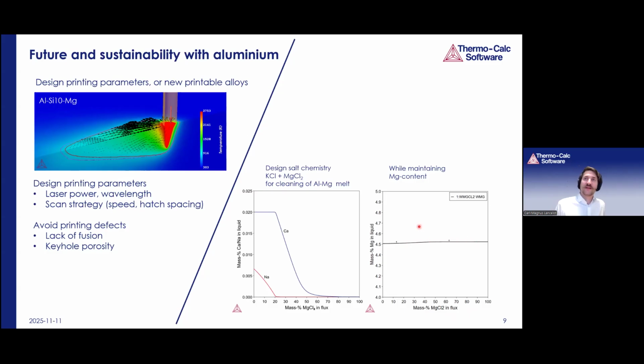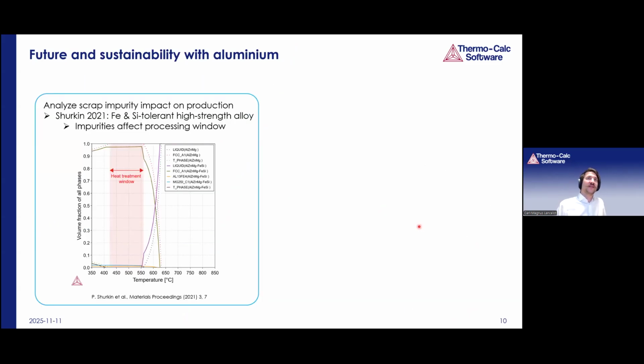So we can see that while increasing the magnesium chloride in the flux, we don't add very much magnesium to the aluminum melt. And then looking forwards into the future of scrap-tolerant aluminum alloys, there are several publications out in literature where Thermo-Calc is used to design new types of scrap-tolerant alloys. These are mostly cast alloys, of course, because cast alloys are a bit easier and more tolerant to the impurities.